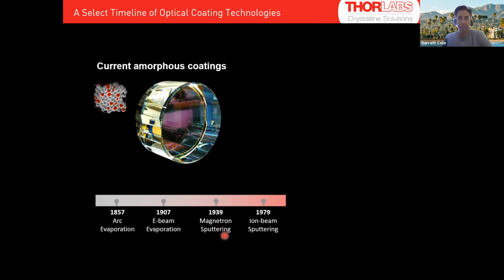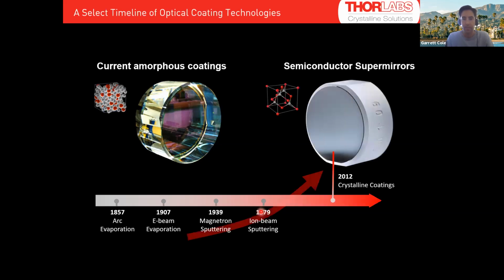And again, in terms of these physical vapor deposited structures, the gold standard would be these ion beam sputter films developed by Litton Industries for their ring laser gyroscope product line in the mid to late 1970s. I'm putting this out here just to show that the ion beam sputtering technique gives insanely low levels of loss, high performance, which I'll highlight. But it's a very mature technology, right? You have 40 years of experience here. Our crystalline coating technique is much newer.